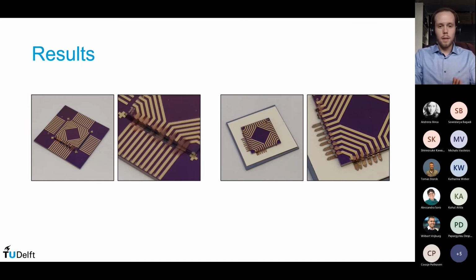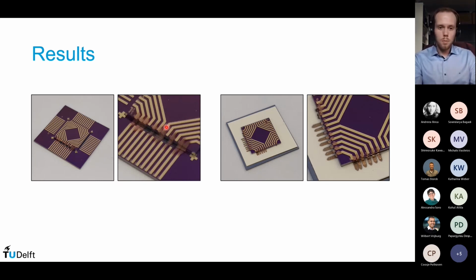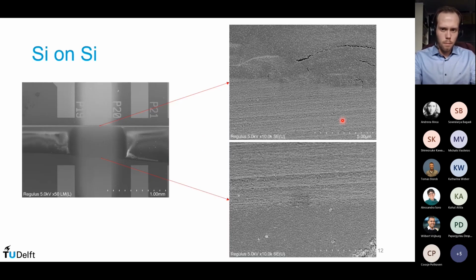So what does the product look like then? For silicon, it's pretty much as you would expect. You have a gold line running from the top to the bottom, following the sides quite nicely. And on the paper, you also can see this process is working. You can even see on the shiny part here is where it's printed on the glue itself, which flowed out a little bit over the paper. And the more darker areas are the paper itself.